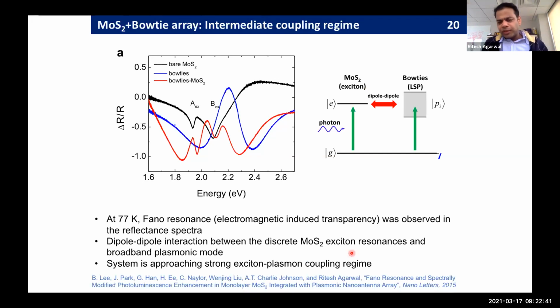Then, as we improved our designs, and the material improved, and our fabrication improved, my students started to report something very interesting. In the differential reflectance spectrum that you see here, if you just have the two-dimensional material, you have these two very nice excitonic modes, or excitons. And this blue curve is just the plasmonic cavity. If we tune one of these plasmonic modes and bring it close to resonance with, let's say, the A exciton, this is the hybrid system. So now we fabricate these plasmonic crystals on top of the MoS2 layer. Clearly, we started to see this splitting in the excitonic spectrum.